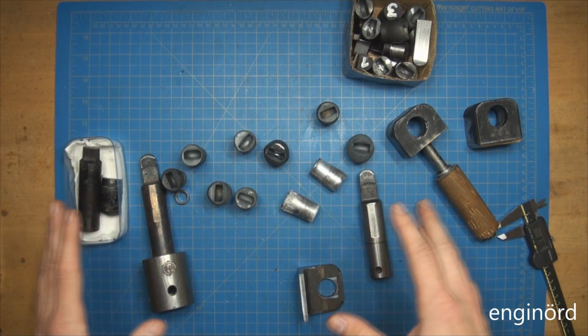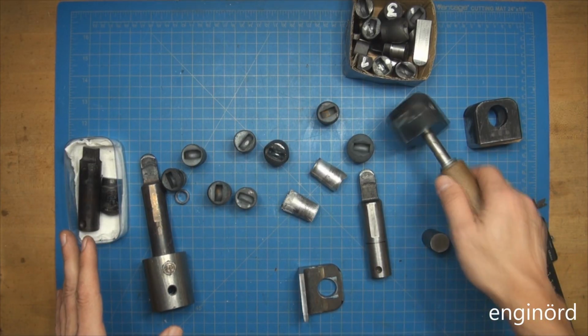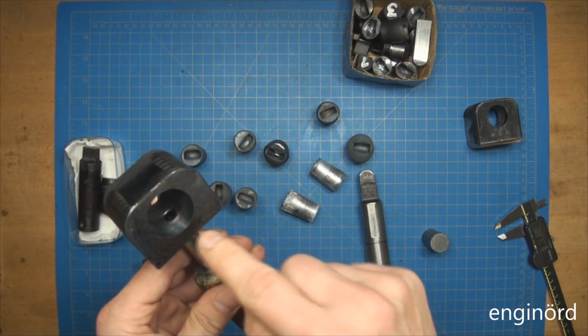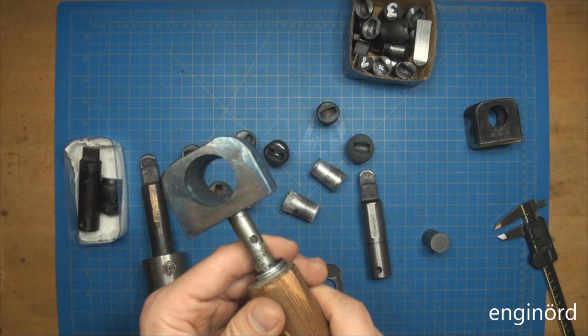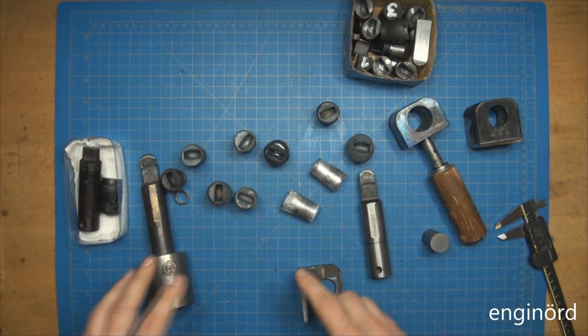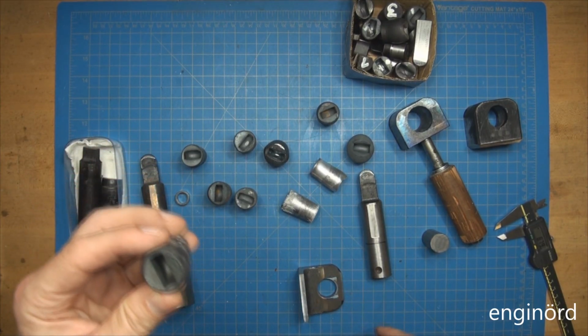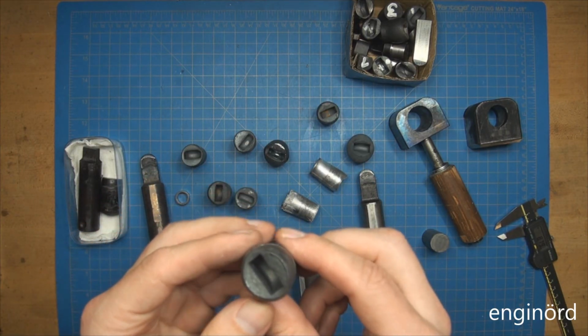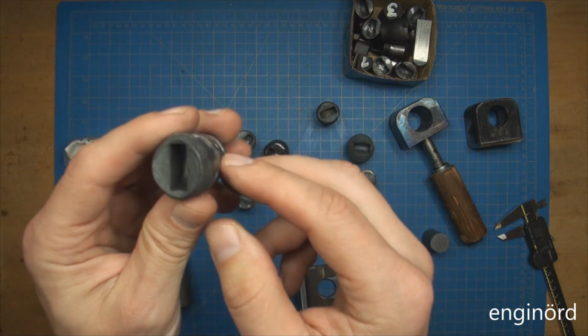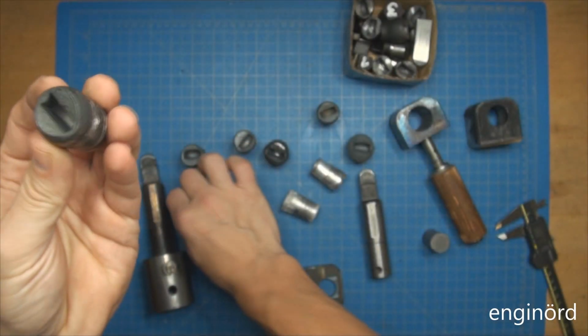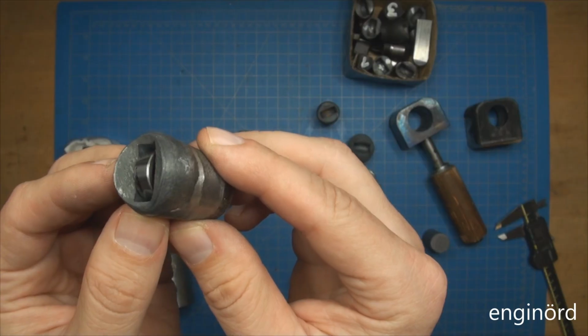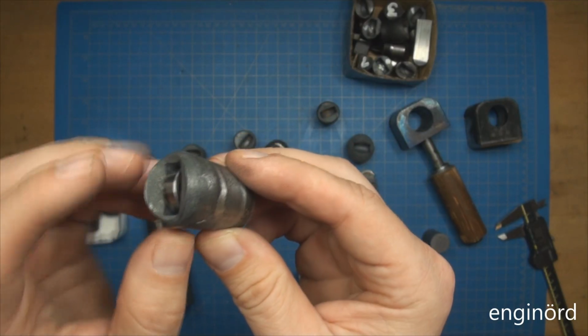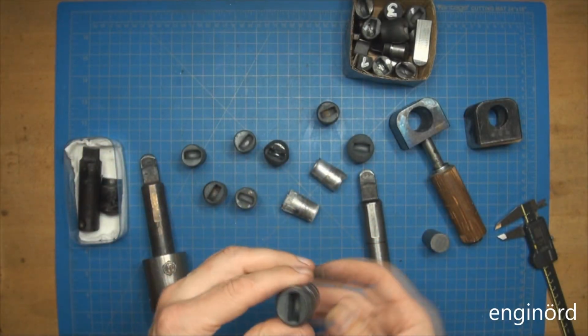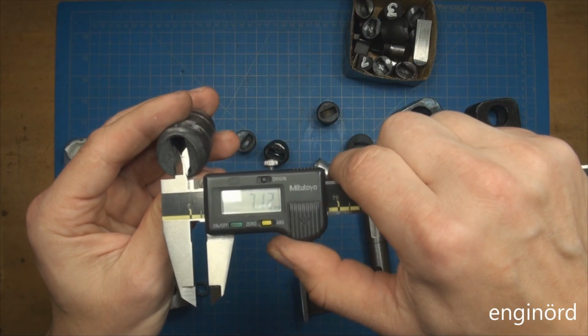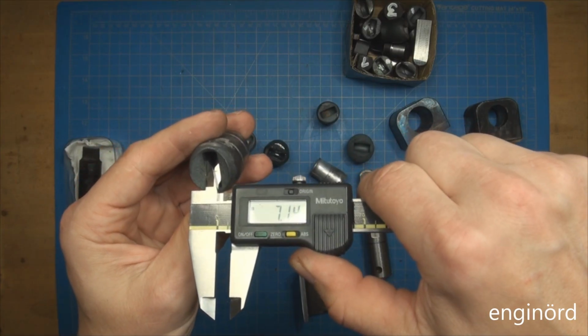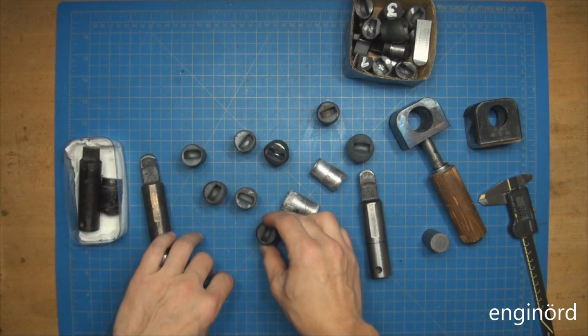From all that I said, all that 9, maybe 10 different improvements, everything seems to be working, except maybe the lower die. I just need to make a new one that doesn't have a hole poking through, and just maintain this geometry, because that was giving me a really good performance. So again, this part was made with the O1 tool steel, and you can see that it has a nice uniform pocket. The roller is sitting there fully. I mean, it has to go down maybe 0.5 millimeter, maybe 1 millimeter, but I can do that by adjusting the depth of the stroke. And then this part measures about 7.1 millimeters at the tip, so that would be a reasonable, acceptable solution for this.